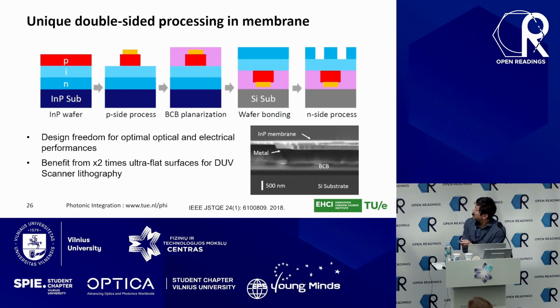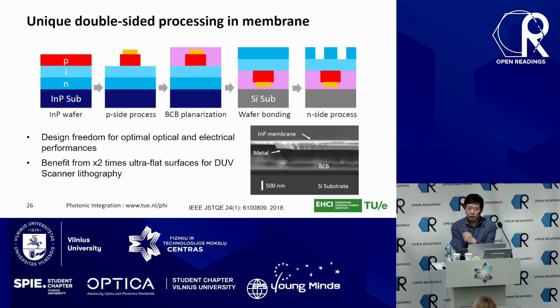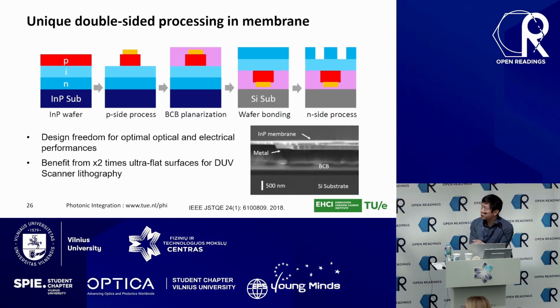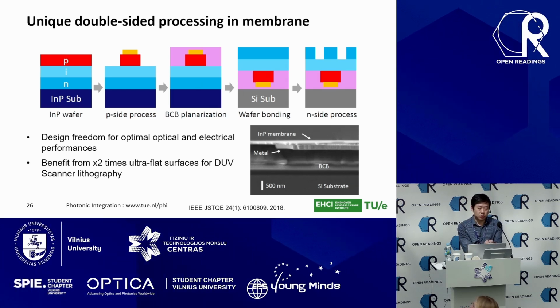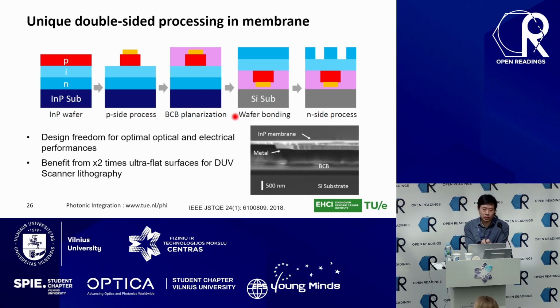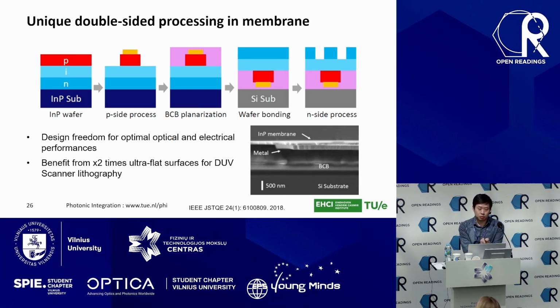And how do we do this? We use a unique double-sided processing. It means that we can process the semiconductor wafer before the bonding. For example, we start with an indium phosphide wafer with a complete layer stack. We can do processing from the top side to form some mesa structures and also electrical contacts. Then we can planarize the surface, and then we flip the wafer to bond it onto a silicon substrate. And then you can see here we can remove the indium phosphide substrate, leaving a membrane somewhere here. After removing the indium phosphide substrate, we can achieve again a very flat surface, and then we can do further processing on it.